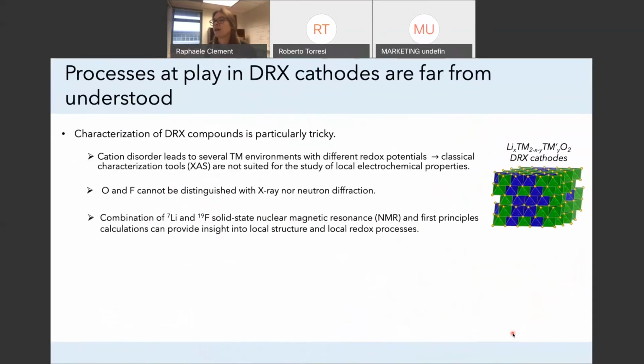Okay, so this is giving you an overview of the performance of these materials. However, there is a lot of research and development ongoing here, and the main point is that the characterization of these materials is particularly difficult. Cation disorder in this case leads to several transition metal environments, and these have very different redox potentials. And so often the classical characterization tools that we use in battery research are not suited for looking at local electrochemical properties, which is what happens in these materials.